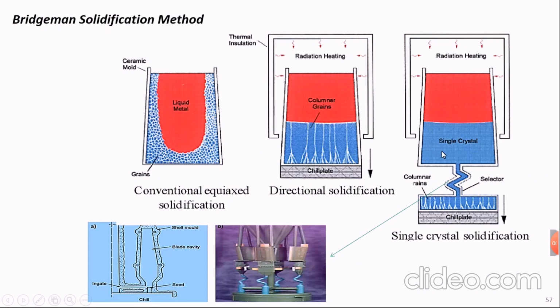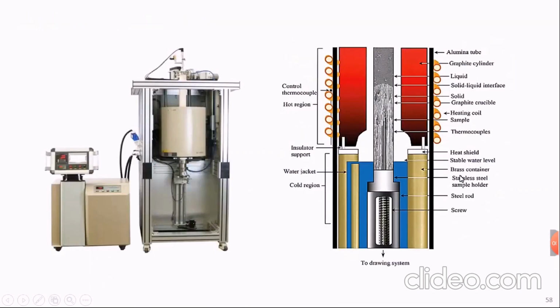In the case of Bridgman solidification, we insert the grain selector, which is prepared by investment casting with wax. And when we insert this seed in the way of the melt going out of the furnace or of the melting chamber, this seed selects only one grain, as you will see. Here, this is the real photo of the Bridgman system. This is the melt being cooled and drawn.